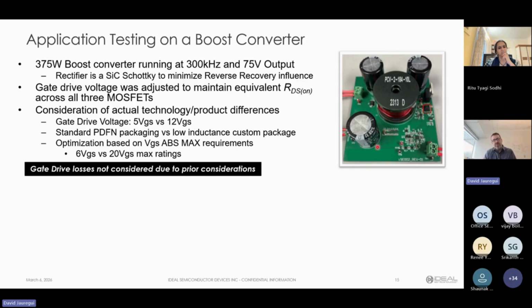So we took those same three MOSFETs and we redesigned this board to be the same, as close as possible. We used the same gate driver. We adjusted the gate resistor. We adjusted the gate voltage for the GaN device because the GaN device could only be driven with 5 volts. If you go to 6 or greater, you break the device. And we adjusted the gate drive voltage on the silicon MOSFET so that the RDS(on) would be the same for all three. And because of the differences in the gate structures, that's going to drive differences in gate drive loss.